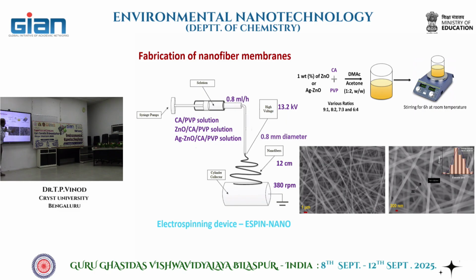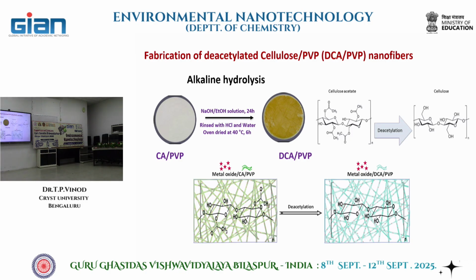And this is one representative image of the film we are getting, SEM image. And then the instrument we used is this one. This is a custom made machine which we purchased from some company in Chennai. So this cellulose acetate PVP membrane, that's not physically very strong. To make it more strong, you can do some process which is called deacetylation. Deacetylation is this process. It's actually basically a base treatment in ethanol. So deacetylation is happening. You can see the color is changing, but the physical strength is increasing. Also, the hydrophilicity is increasing due to that treatment because acetyl group is removed.